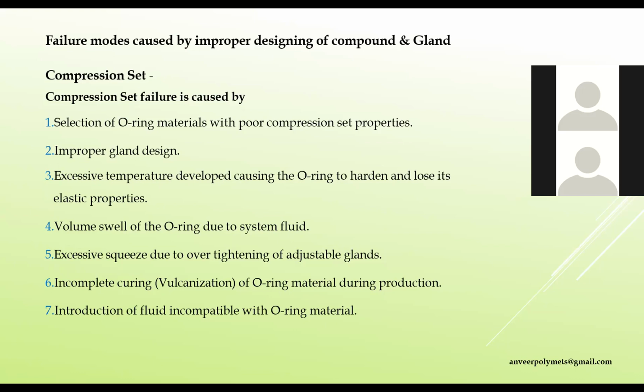So which factors contribute to compression set failure? First, selecting an O-ring material which inherently has poor compression set, or improper gland design. If excessive temperature is developed during application, then the O-ring gets hardened and loses its elastic property. Temperature can be developed because of the system fluid, external environmental factors, or frictional heat buildup. Then volume swell of the O-ring due to system fluid: if the O-ring absorbs excess fluid from the system, it swells, and because of that swelling, compression set is hampered. The next reason is excessive squeeze of the O-ring due to over-tightening of adjustable glands.